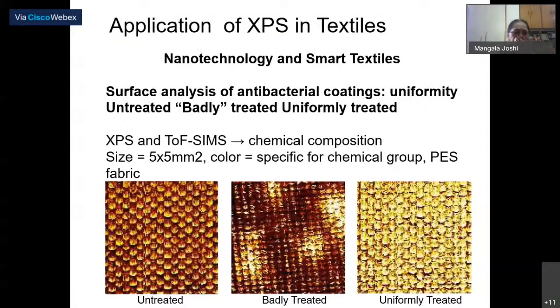So this is now the actual samples of uniformity. So you have the untreated sample, you can see the fabric, they have treated with some antibacterial coating. So the middle one has been badly treated. This is an XPS image. So you can see the image, it is not very uniformly coated. And on the extreme right, you can see the image where the sample has been uniformly coated.